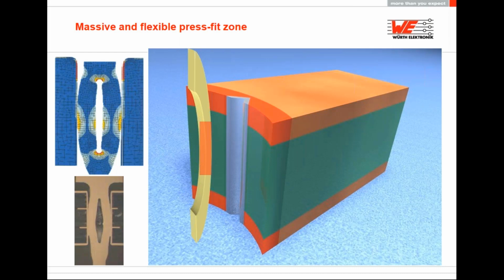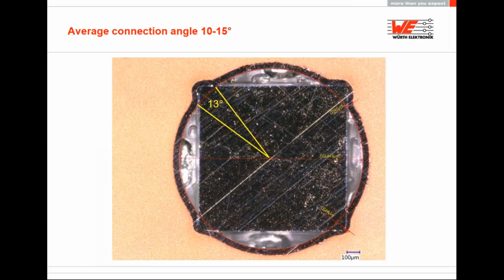Although there is no cold welding process because of the low forces, the benefit is that there would be no deforming of the via on the PCB, nearly non-existent. The pin is deformed, so if the pin is deformed, the PCB will not be. That gives possibilities for connection, like fast-on connections, but still the current capability is smaller.